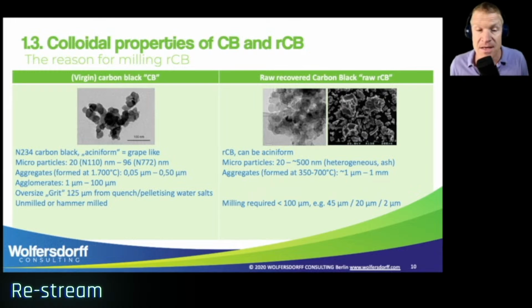And in some applications like rubber extrusion, the grit is very important. Grit can come from oversized particles coming from the quenching water or the pelletizing water. And this typically has the size of 125 micron. So there are special rubber extrusion carbon black grades that use demineralized water for quenching and pelletizing to avoid these salts. Also, typically carbon blacks are unmilled or they're coarsely hammer milled.